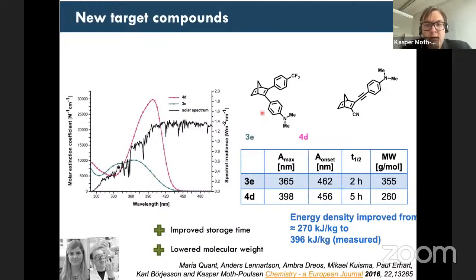So if we compare the best original, our first series of molecules, with the second one, you can see that the optical profile is quite similar. The onset of absorption, which is what we are mostly caring about, is more or less the same. The storage time is also more or less the same. It's not super long, only a few hours, but the energy density is much better, with much lower molecular weight and much higher energy density. So this was all good at the time.